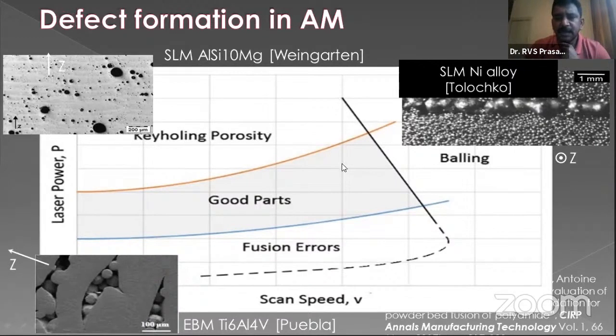And at the same time, when you have a very high laser power and scan speed, there is a phenomenon called balling. That means it will just simply push the powder without proper melting. So you will end up with a balling kind of phenomenon.